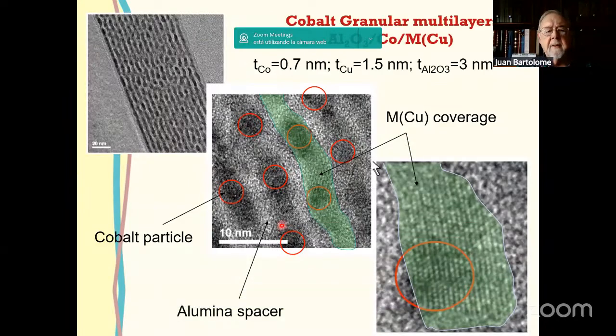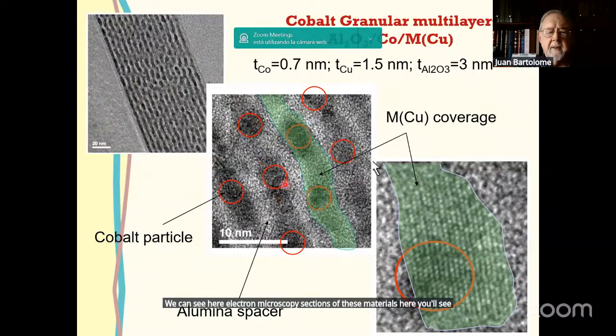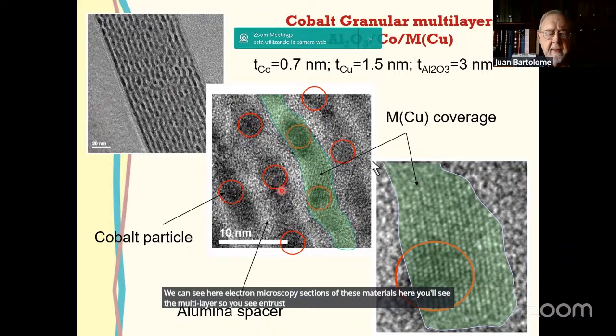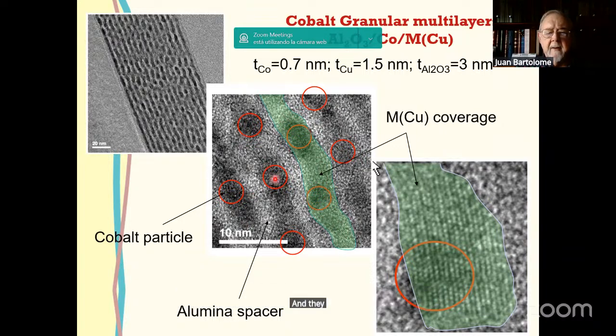We can see here electron microscopy sections of these materials. Here you see the multilayer. Here you see, enhanced, the cobalt particle and the copper. In the case of copper capping, it surrounds the particle and also connects one particle to the other. And they are separated one sheet from the other by the so-called alumina spacers.